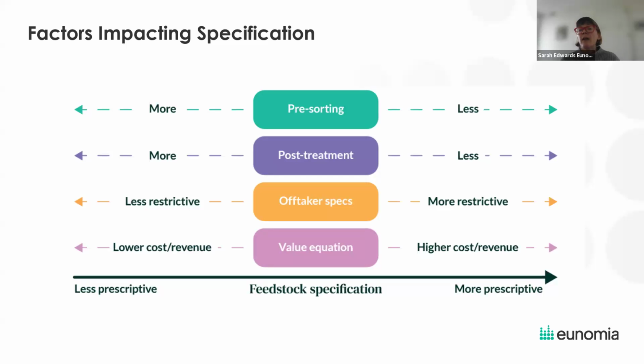The other factor that affected the feedstock that they were sourcing was any post-treatment, so this is of the pyrolysis oil. Again, the more post-treatment there was, the less stringent to some extent the feedstock specification was. And the requirement of the off-taker, effectively the requirement of the cracker that would be taking the pyrolysis oil, also impacted to some extent the processes I mentioned before, the pre-sorting and post-sorting that need to be done, and therefore the specification.